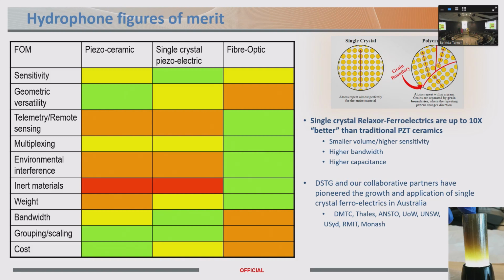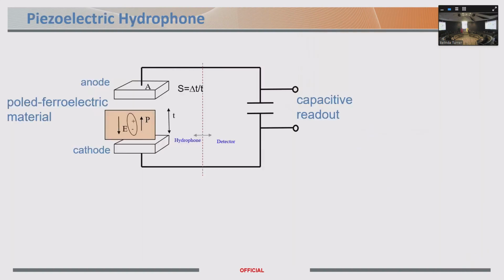And what you can see right down in the bottom right-hand corner there is a crystal that we developed with a whole bunch of partners, which I've listed there. I'm going to see if I can pronounce it, PMNPT. So it's lead magnesium niobate, lead titanate. It's a ternary single crystal piezoelectric material, and this is the first bulk single crystal billet of this material that was fabricated in Australia, only about 2 or 3 years ago. And this was grown using the Bridgman process, and there are a couple of different processes that can be used to make these materials.